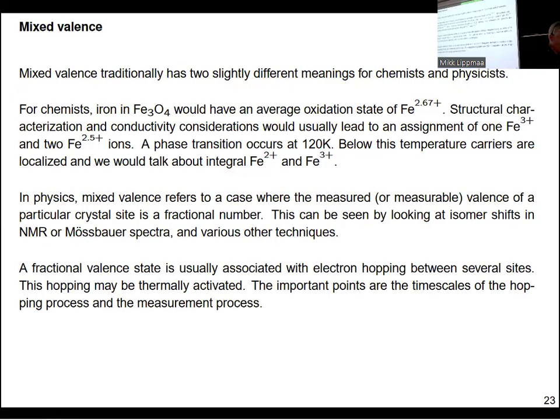Then we come to another aspect, which is mixed valence. And mixed valence is actually quite an important feature, which has a slightly different meaning depending on how you look at your material. So if we look at something like magnetite, Fe3O4, we can see that the iron's average oxidation state would be 2.67. But actually, what we see is that it's a mixture of iron 3+ states and effectively iron 2.5+. This transition happens at 120 K, the so-called Verwey charge ordering transition. So there is actually a distribution of Fe2+ and Fe3+ states in the material. We will look at that when we look at the spinel structure.